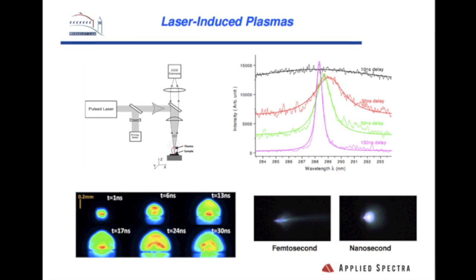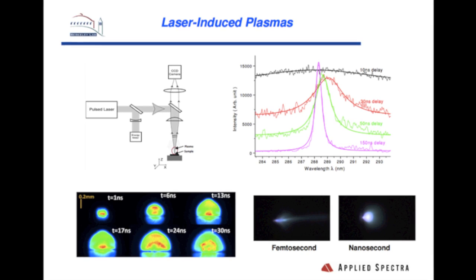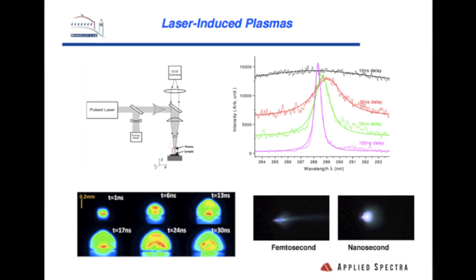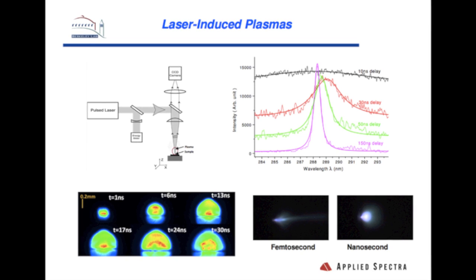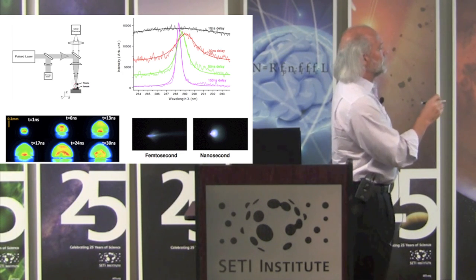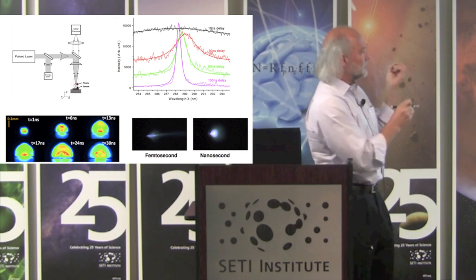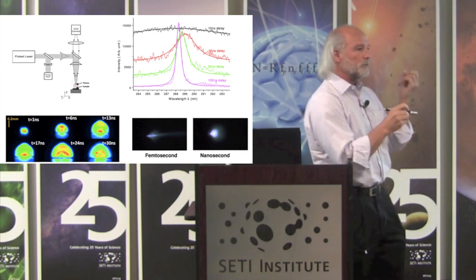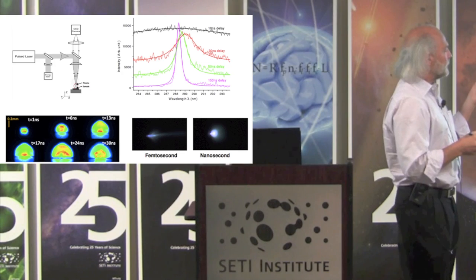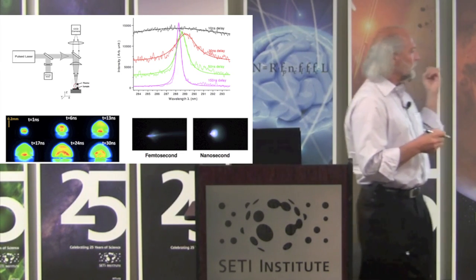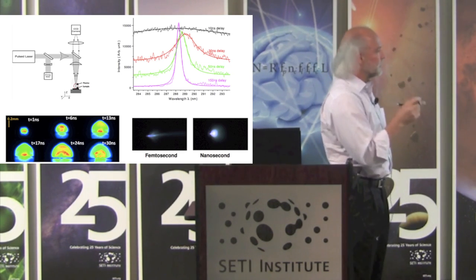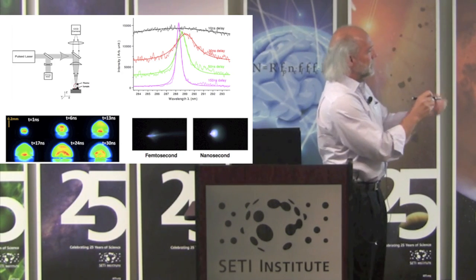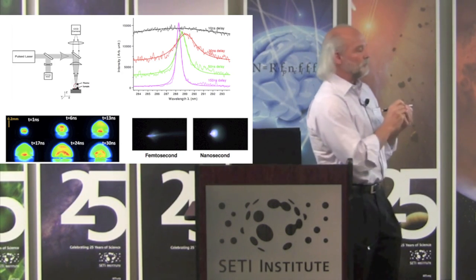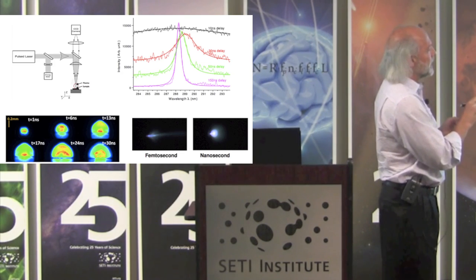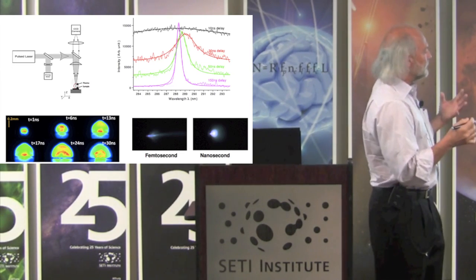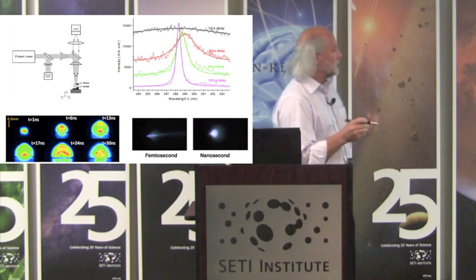Just a little photograph. I told you there's a big difference between a femtosecond and a nanosecond induced LIBS plasma. This is a target right here. Laser came in, hit the target. This is just a photograph. So we had the same energy of the laser, the same wavelength, the same spot size, the same sample. The only thing that was different is the pulse duration. The femtosecond was 100 femtoseconds, and the nanosecond laser was about 4 nanoseconds pulse duration. Because, like I told you, that nanosecond laser actually will heat that plasma. So you can see it's a much different type of plasma. The time relaxation process, cooling processes, everything is different.